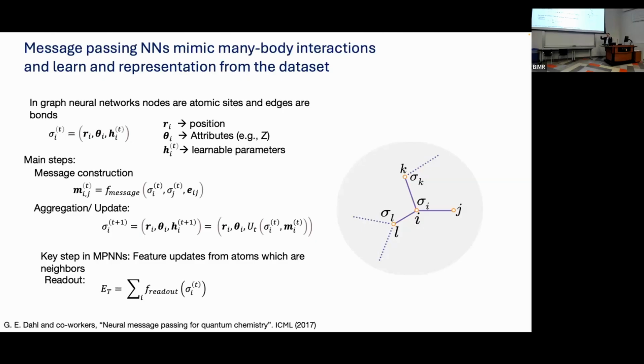So that would be simply summing all of the different node attributes, the communication between the nodes, the messages together, and creating an average or taking their maximum. There's different ways you could aggregate that information, but usually some summary statistic from all the nodes within a certain cutoff. And then you perform this over and over for some number of steps or layers, and that is how you update it. And eventually you get a set of node features, sigma_i, at the last layer, which you can then collect in order to create the total, in this case, the total energy. You define some function that maps from the sites themselves to the total energy. And this is your neural network potential.